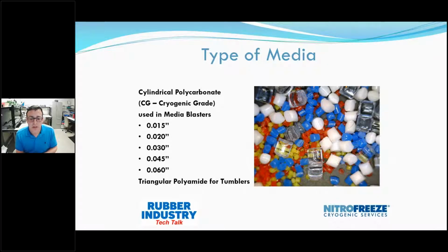I find that if we were to run, say, a rubber part in particular, you're going to run into problems, because what ends up happening is the media will chip away where the flash is attached to the part. Using a smaller media will remove the flash, but it's not going to induce any damage. It's not going to start chipping and eating away at the part. So the bulk of what you want to do is somewhere between 15 and 30 thou, and that's going to be largely dictated again by part geometry.